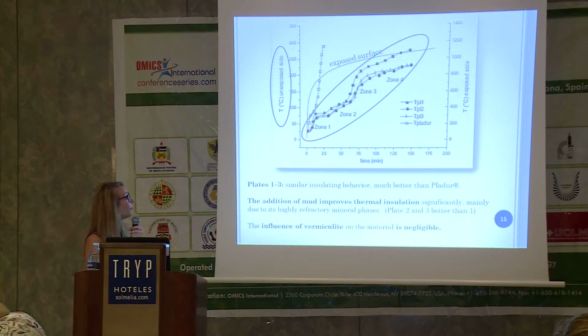But plates 2 and 3 have a slightly better behavior. It is because the addition of mud, the first waste, improves thermal insulation significantly, mainly due to its highly refractory mineral phases. However, the influence of vermiculite on the material was negligible.